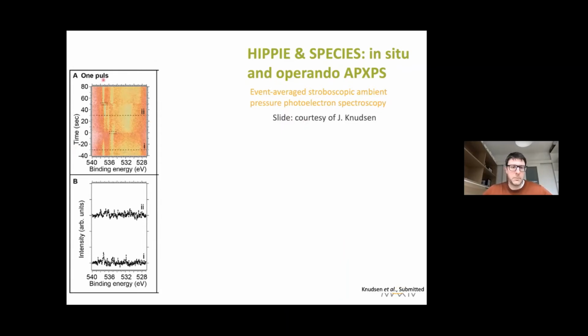This picture shows a series of oxygen 1s spectra, just from one pulse with the 6.5 Hertz acquisition rate. You do actually see some of the changes here. The gas lines you can resolve by eye, maybe not very well. There are also some changes happening on the surface that you can barely see. However, if you look at the data spectrum per spectrum as shown here, it's just all signal within the noise. So that's not really fittable, and you need to improve statistics.